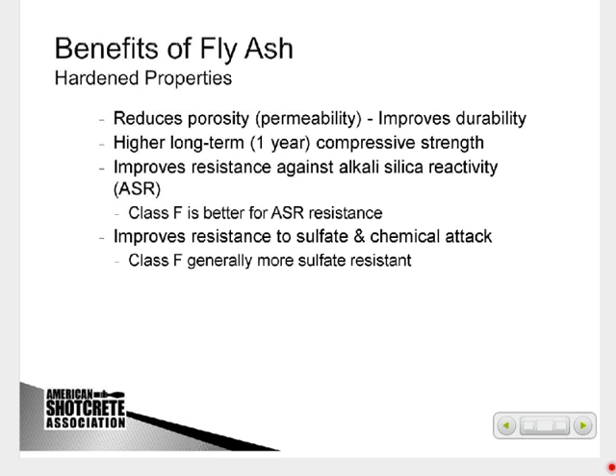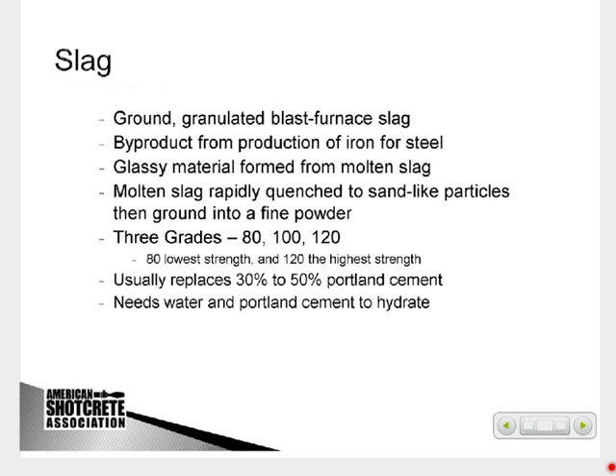It does reduce the permeability or porosity that increases durability. It has a little bit higher strength long-term, a little slower at 28 days, but it does build long-term. And it has some ASR resistance, which can be a benefit for shotcrete in areas that might have an ASR aggregate or prone aggregate.